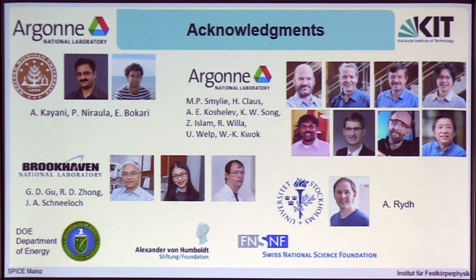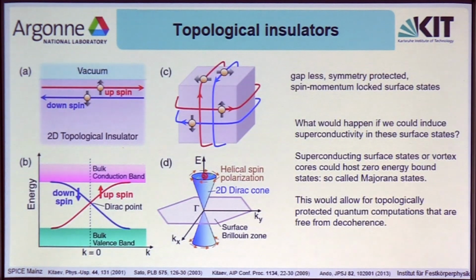Okay, so doped bismuth selenide. As you might know, bismuth selenide is a topological insulator. Let me start by introducing this one. A topological insulator, in contrast to a band insulator, where we have the Fermi level and the band gap between the valence and the conduction bands and no states available for conduction, has, due to strong spin-orbit coupling, this band inversion, which leads to a crossing of the bands at the Fermi energy, and thus makes surface states available on the surface for conduction.